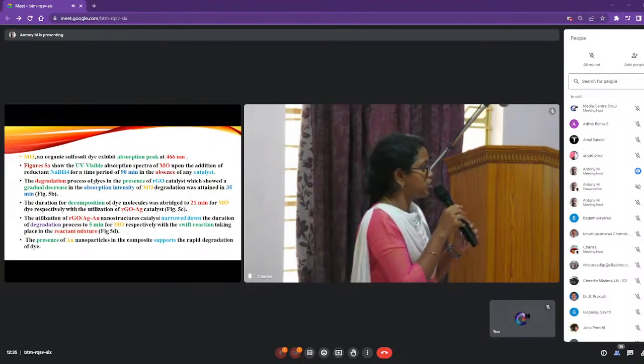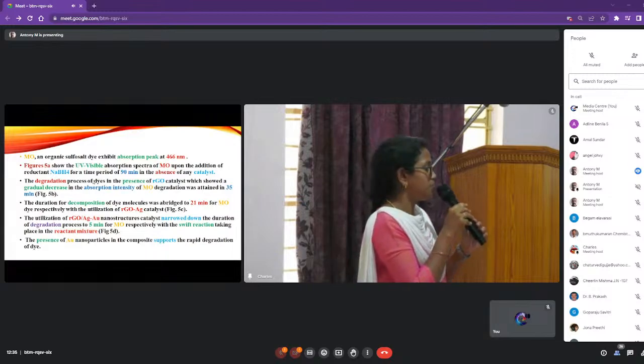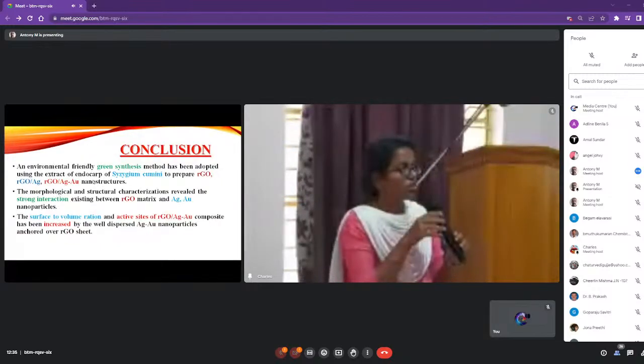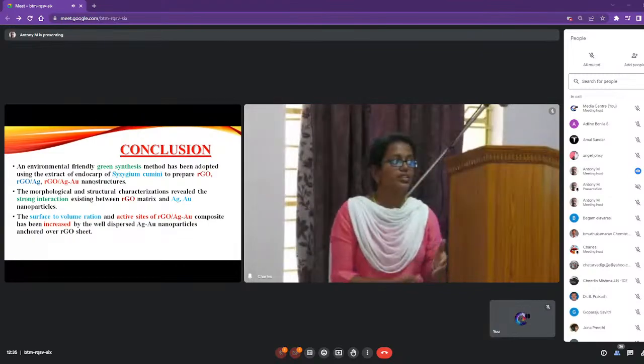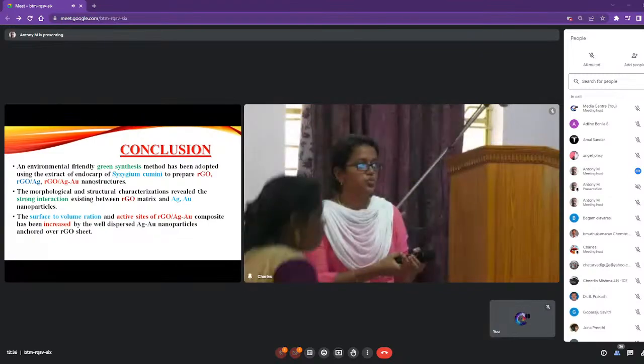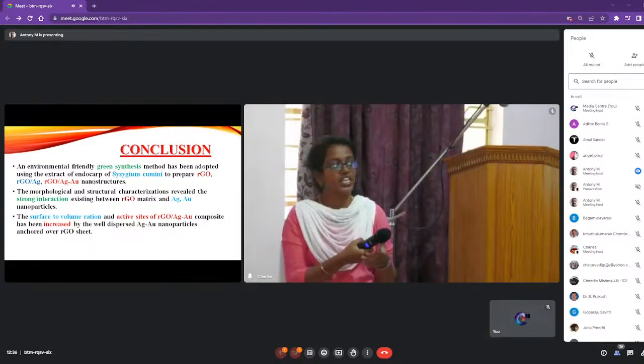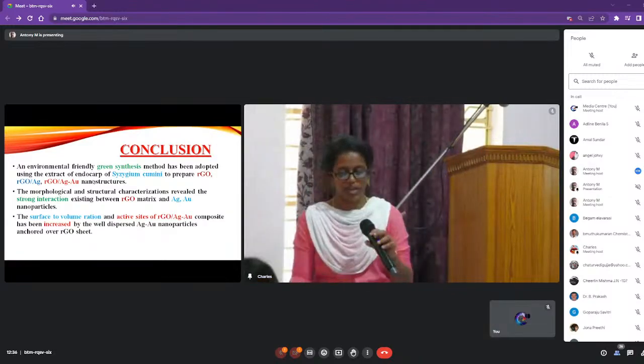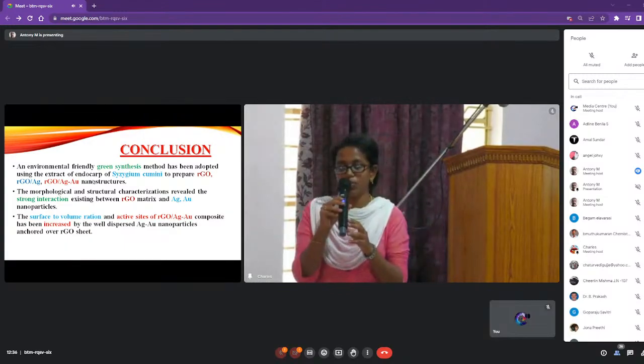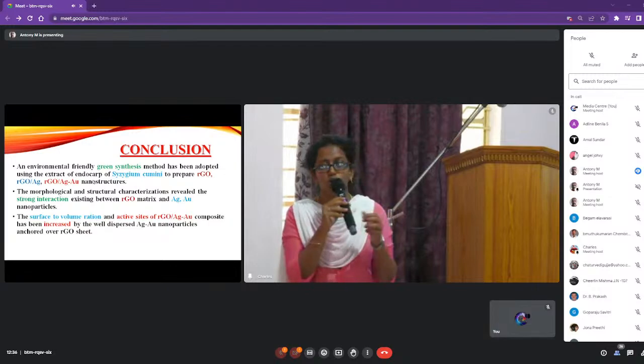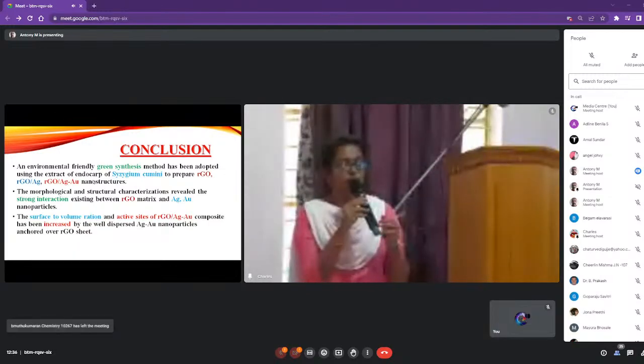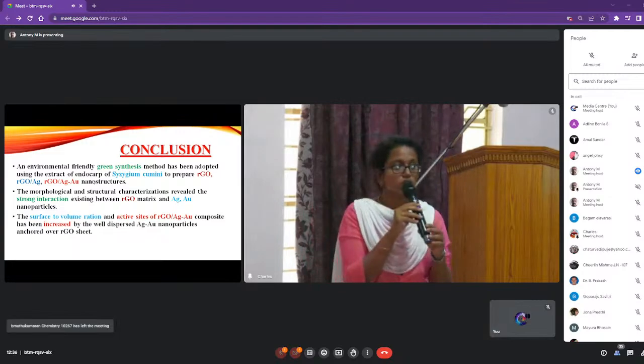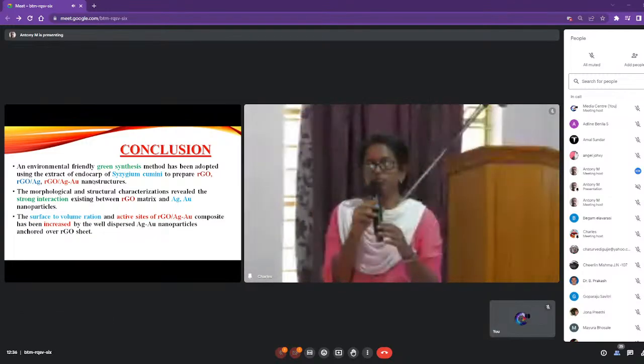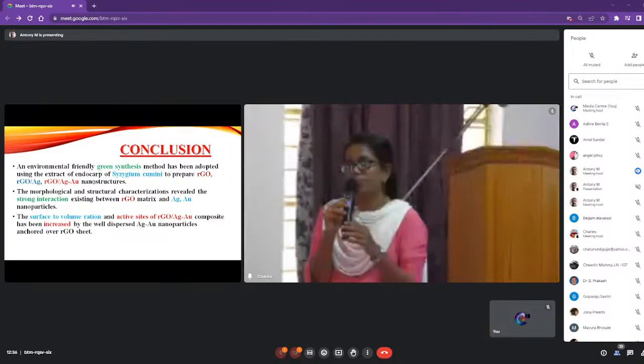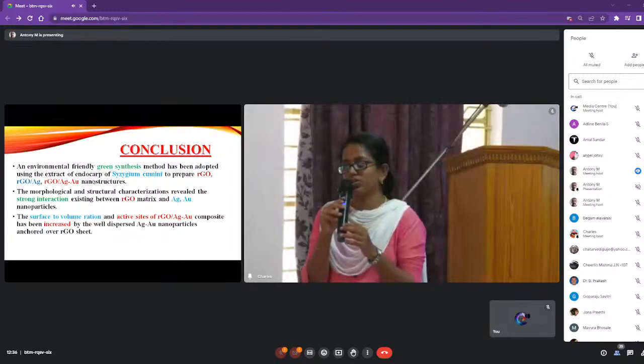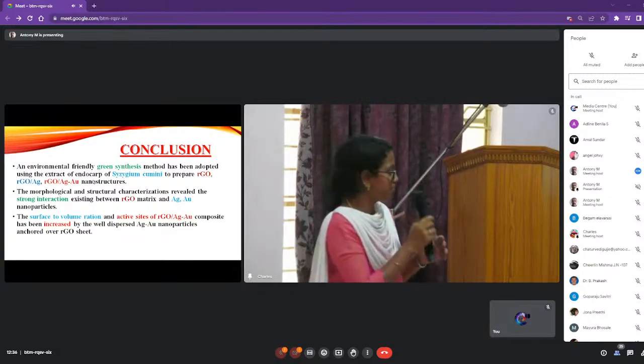that by adding the catalyst, the degradation process is completed in 5 minutes. From this, I conclude that this is an environmental technique, a green synthesis method. Using this extract we can prepare reduced graphene oxide-silver composite and reduced graphene oxide-silver-gold composites. So this catalyst speeds up the degradation process, so that we can reuse the water, which results in a solution for water scarcity. Thank you.